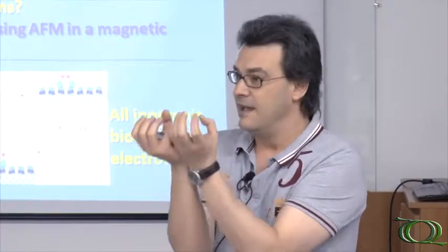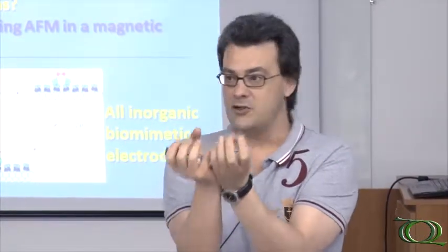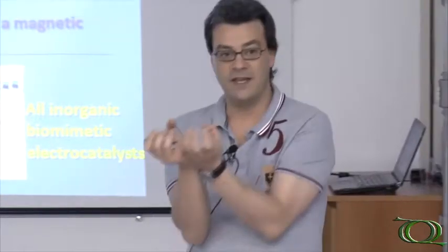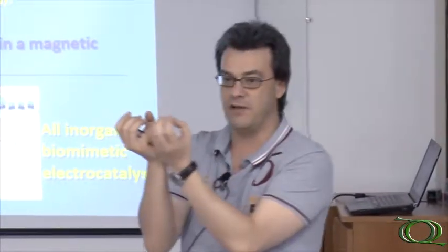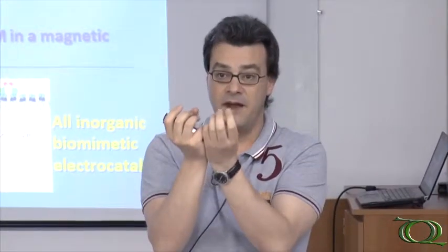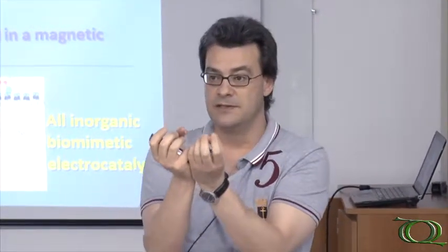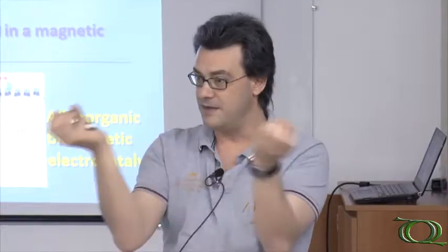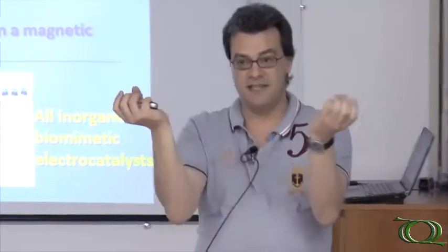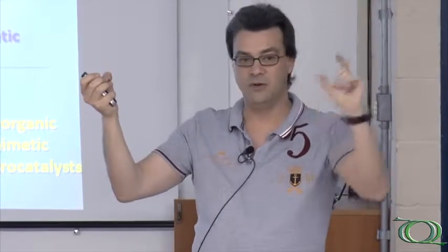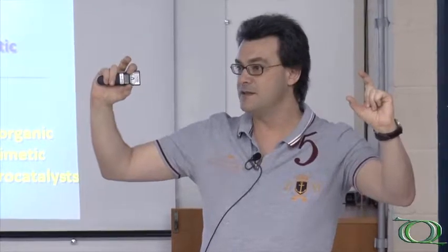But this is not the only thing. They are placed at a distance at which they can form a peroxo bridge. So they can bind an oxygen molecule with an oxygen bond to each one of the atoms. And they are in a place which is very flexible, so they can move and change that distance. So once they form this peroxo bridge, they can break the peroxo bridge, separate, and you have 2 metal-oxygen bonds. Then protons come and you release water.